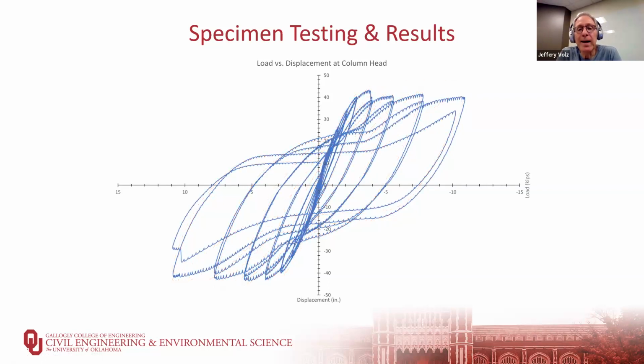Before I do that, we ended up having a peak of about 43 kips for the maximum lateral load. And it's important to also see that there was degradation in the peak for the SCC column. Not a lot. We get down to about 40 kips, maybe 39 kips, but there was some degradation.